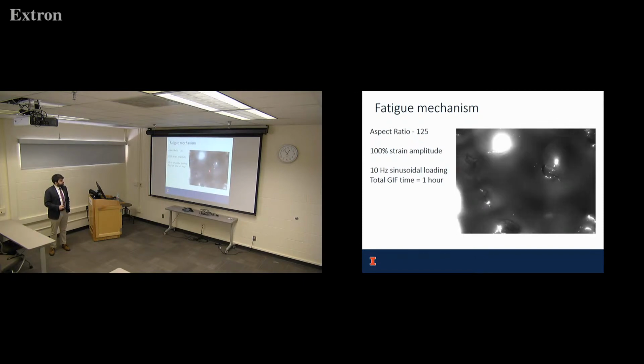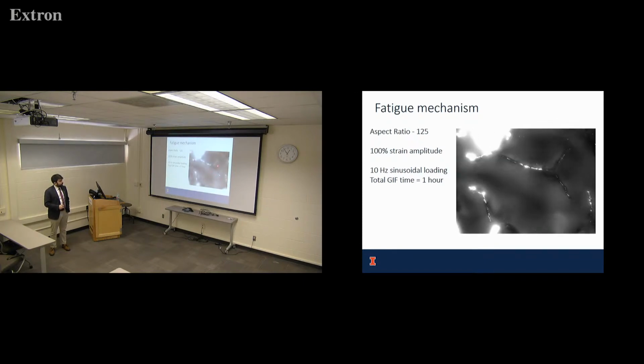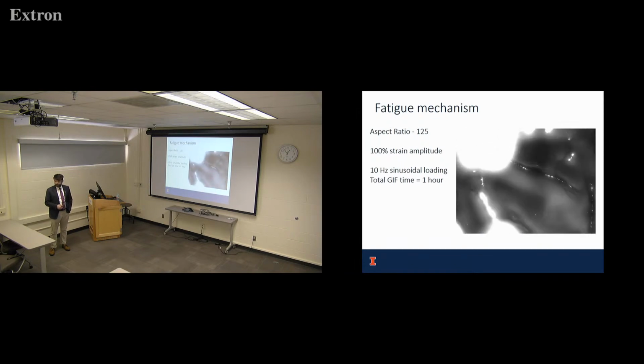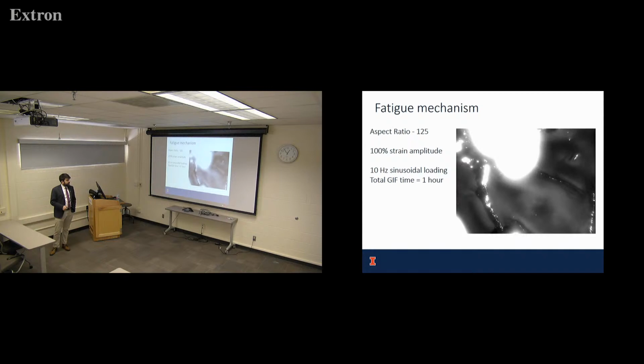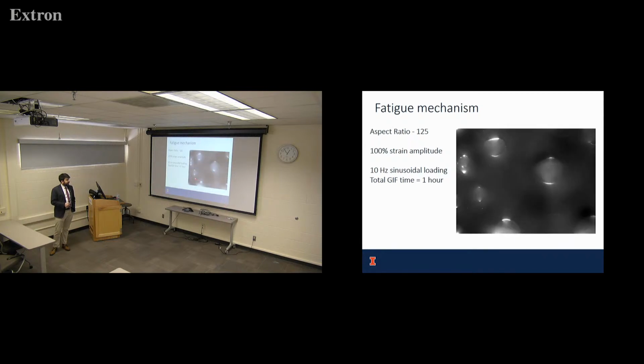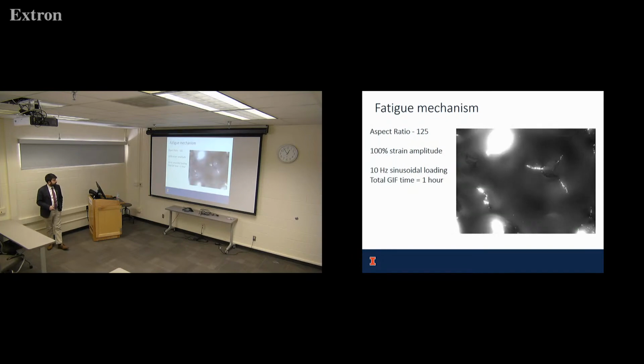You'll also notice that those bulk microstructures start shifting away from where those cracks are forming and shifting into the areas that are undamaged. So all of those microstructural features tend towards those undamaged regions, and in those damaged regions, you start to see those microstructures aren't really there anymore.